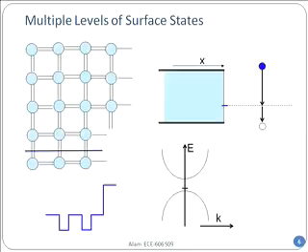This is because anytime you have a surface, you cannot have an absolutely plain surface. Not possible. Anytime you cut it or break it, what happens? It goes flat a little bit, and then an extra layer of atoms is gone. Sometimes an extra layer, two layers of atoms, are still there. So on the atomic level, there is modulation of the height, going up and down a little bit, on the order of a few angstroms. And this is present anytime you try to terminate a surface, right? So on the bottom side, what I'm trying to show in the left-hand figure is a consequence of the height modulation. And what will happen as a result?